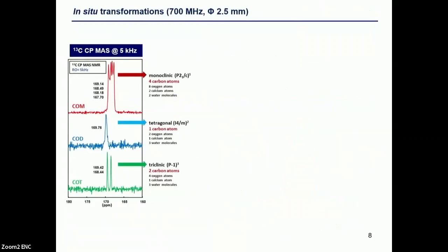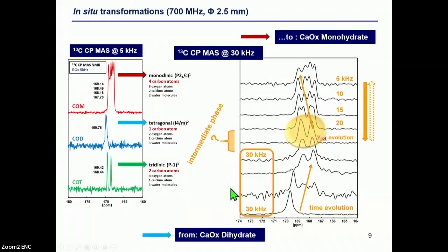If you spin rather slowly at the magic angle, let's say 5 kilohertz, then for the three hydrated phases, here you have the fingerprints, which are clearly distinguishable first, and the number of sharp peaks is directly related to the number of inequivalent sites in the asymmetric unit. But as soon as you spin faster, let's say 30 kilohertz, using a 2.5 millimeter probe, then you see that starting from the dihydrate, which is characterized by the blue spectrum, after a certain time of evolution, you will have a complete transformation of the sample into what I call for the moment an intermediate phase with two peaks, which are a little bit broader than the initial ones.